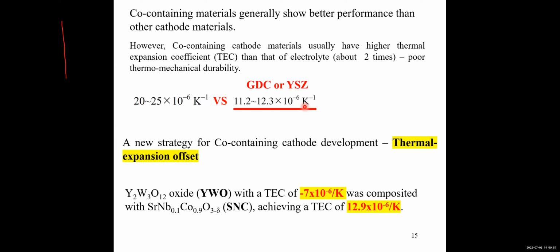Since cobalt containing perovskite materials, such as SNC, have a high TEC value, we try to mix the cobalt containing perovskite materials with other oxides showing lower TEC value. For example, we selected YWO oxide, which showed even a negative TEC value. By mixing these two, we can well control the TEC of the composite.